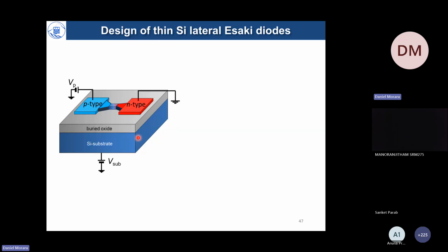But for that, we also needed to fabricate the devices in our lab. So I'm returning to this schematic, because this is a silicon-on-insulator wafer, and we doped it laterally, which is quite different from the typical way of making PN diodes in material science. You make it vertically. We dope the left side as p-type, and we use different masks. When we dope the p side on the left, we cover the right side with a silicon nitride layer as a mask. When we dope n-type on the right, we cover the left side with silicon dioxide as a mask. These are all done by electron beam lithography.